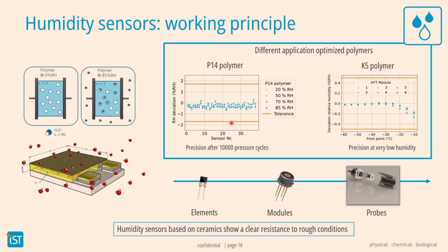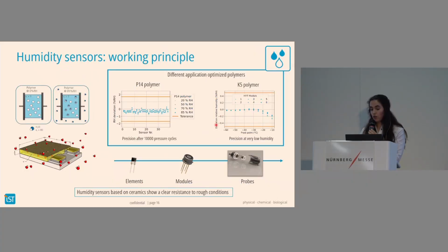Here we have tested it after a stress, which is like different pressure cycles. So we have different samples in a chamber where we put pressures from 0 to 14, and then we test the sensor to see if it's still delivering. And as you can see, the deviation on the relative humidity is extremely low for all humidities. And another one that we have developed for extremely low humidities is the K5 polymer. So here you have the measurements of 6 modules over different frost points. And as you can see, the accuracy also remains quite good despite going quite low.